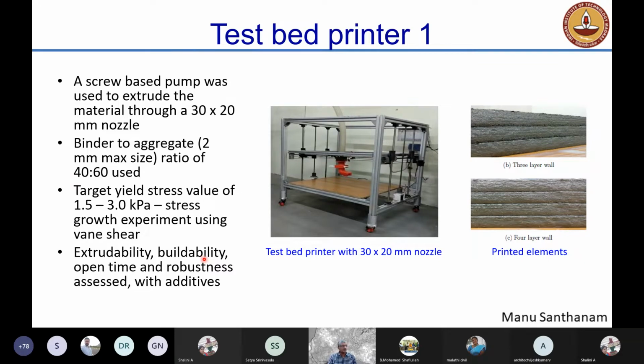structure. So you see some examples of things printed here with this simple printer with a 30 by 20 millimeter rectangular nozzle. We have this 3-layer wall that is printed, 4-layer wall that is printed. What you can see is each layer rests on top of the other, and you see that there is no deformation of the bottom layers. As the top layer comes on top, the bottom layer is able to retain its shape, and that's a good sign of the right kind of 3D printed material.